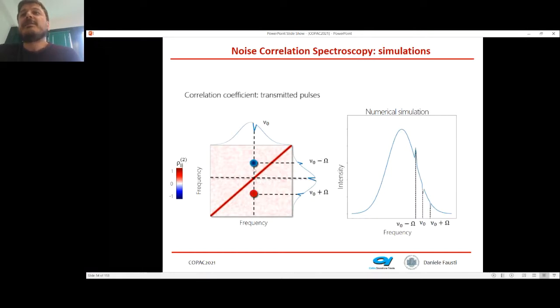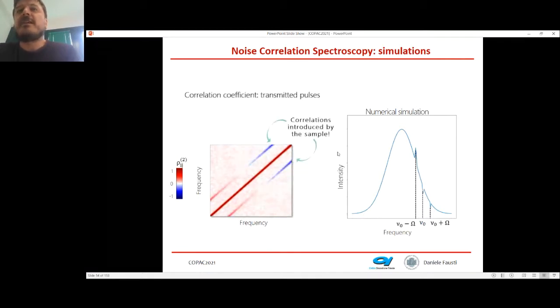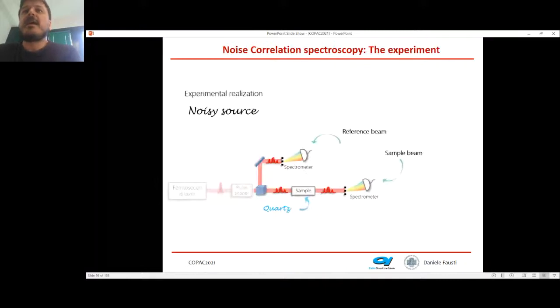then the two frequencies which differ by big omega, where big omega is the frequency of the phonon, are no longer independent. Because if I destroy the photon at one frequency, it has to appear at another frequency. And this of course happens simultaneously on all the frequencies, so I can expect to see correlations at frequencies which are associated with the frequency of the phonon modes. And here are the experiments I'm going to discuss.